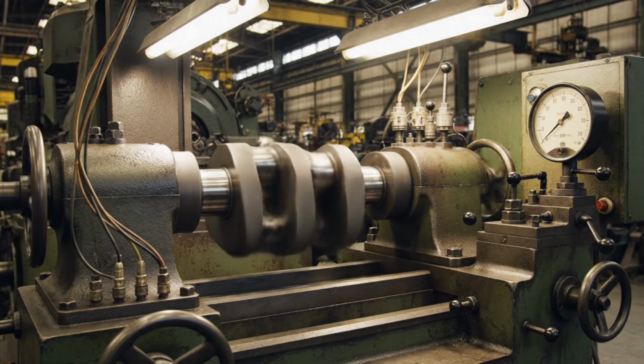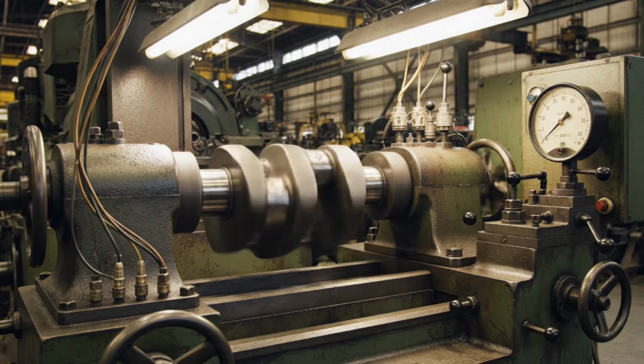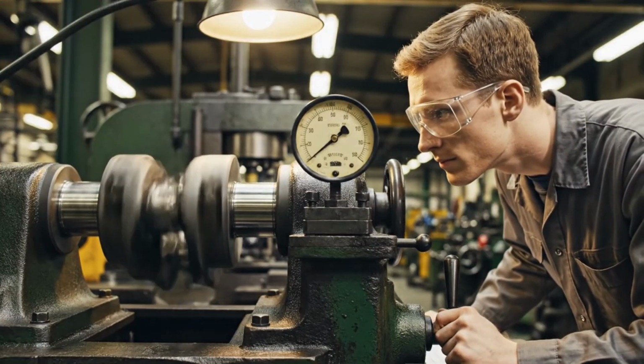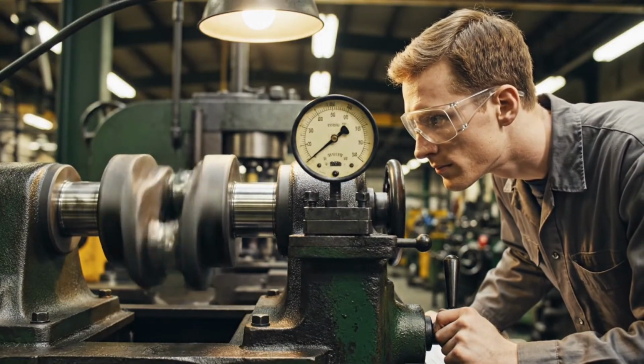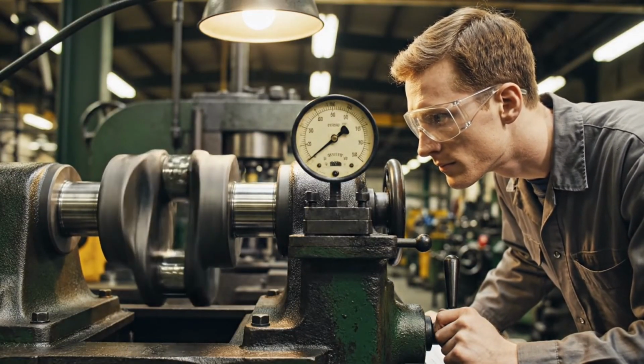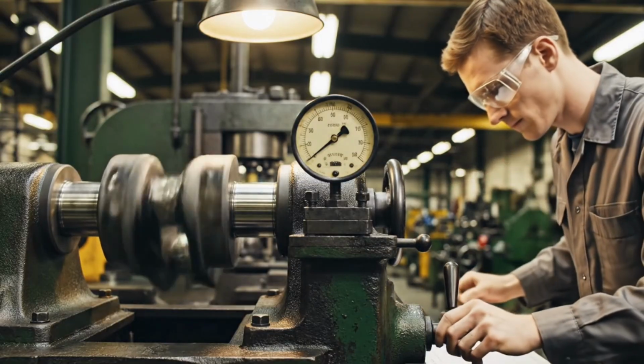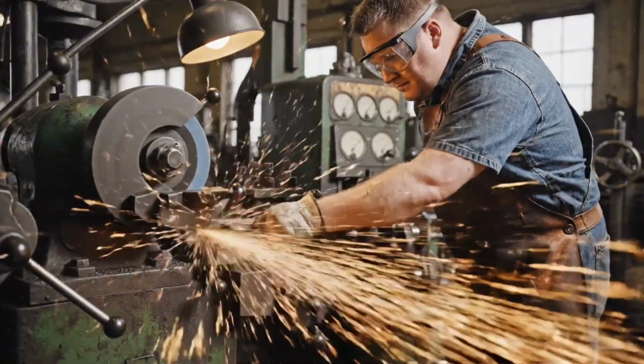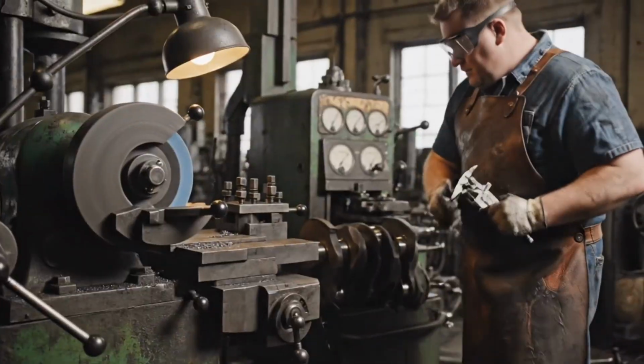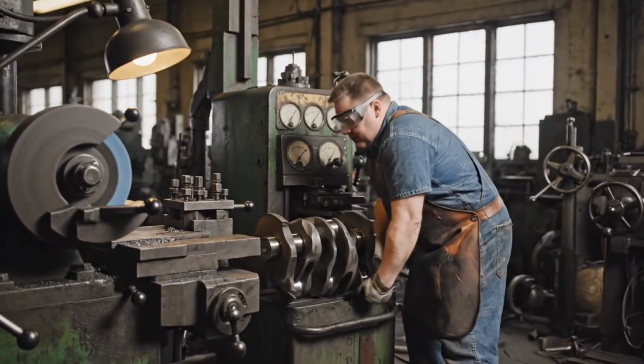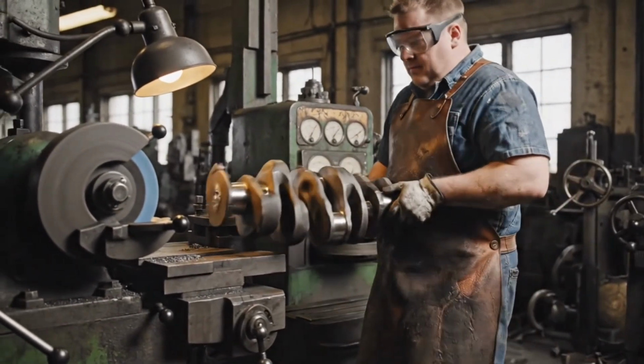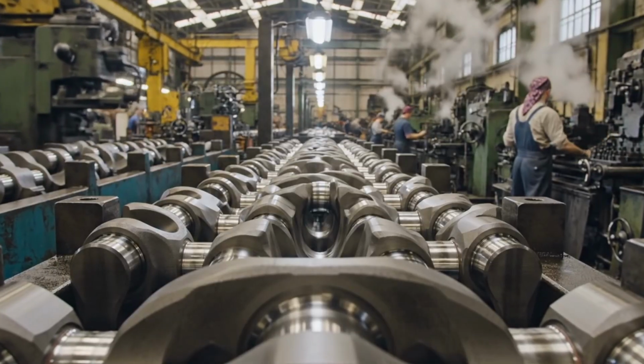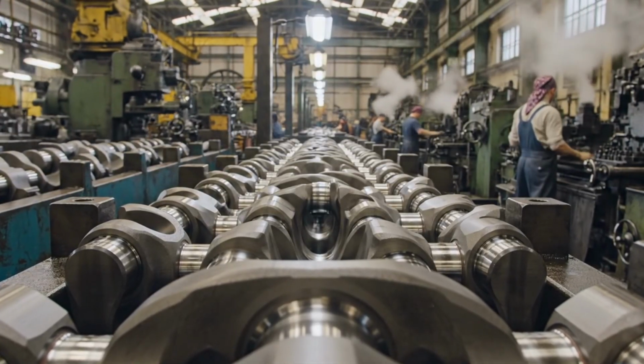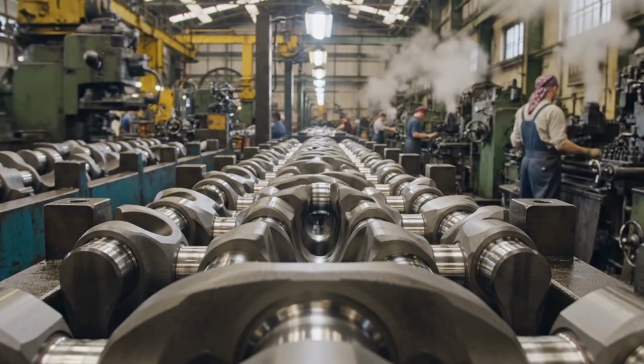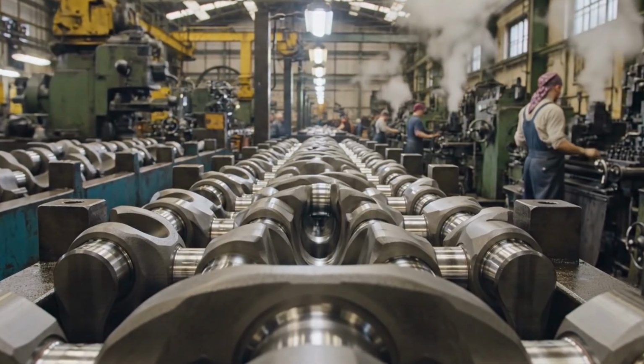Balancing was performed on a dedicated machine that spun the crankshaft at operating speed and measured its rotational equilibrium using vibration sensors. If the shaft was off balance, a machinist removed material from the counterweights by grinding until the shaft spun with no detectable wobble. Every single crankshaft produced for the XA was balanced individually. There was no sampling, no statistical shortcut. Every one had to be perfect.